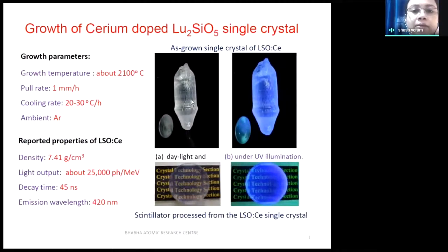To make this for SPECT and PET, you have to use single crystals. You cannot use thin films, because these are high energy gamma photons, so you need a single crystal to absorb them. You also need the energy resolution, and when energy resolution is required, we have to use a single crystal. The growth temperature is 2100 degrees centigrade, so it is very difficult to grow this material.